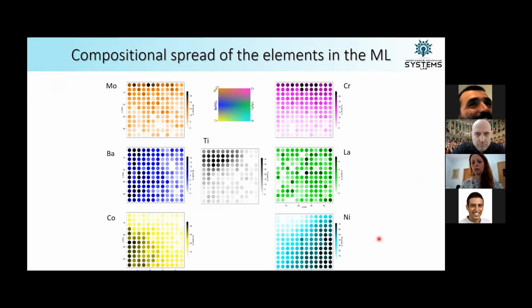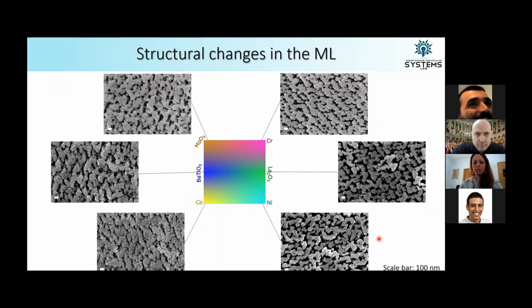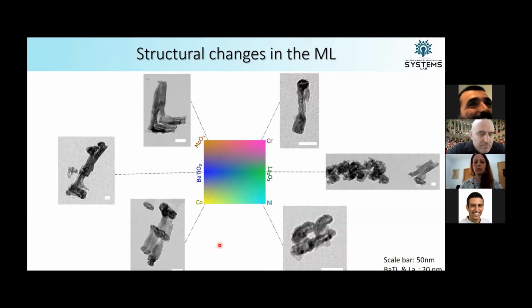But what happens if you look into the nanostructure? So just from SEM images and measuring on the surface, you can immediately see that there are changes. So for example, the lanthanum oxide edge looks like some sort of strange triangle shapes, and the cobalt looks like these round globular shapes. So they're completely different. And when we look into the actual structures by TEM, you can see completely different nano shapes across the library. So you have an L shape, you have this bone or barcode-like structure, a match structure shape, zigzag, and the lanthanum and barium titanate are actually intermediates, and that's due to issues with their vapor flux.